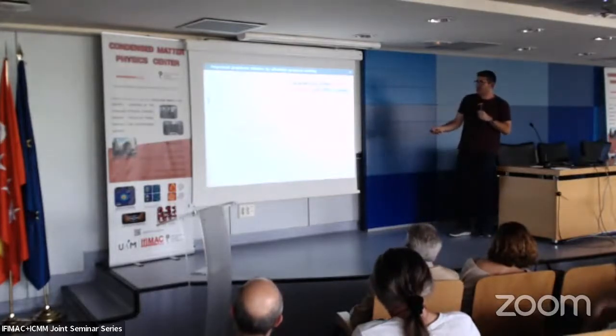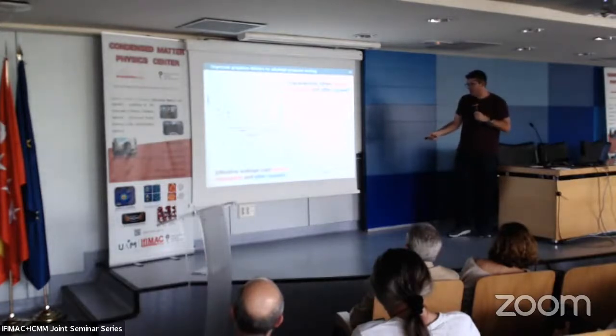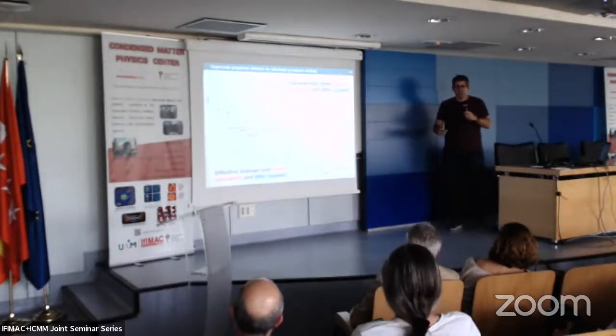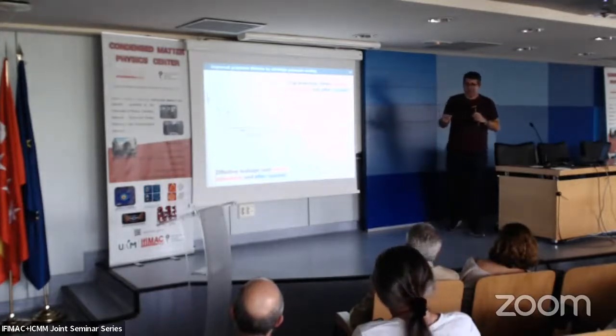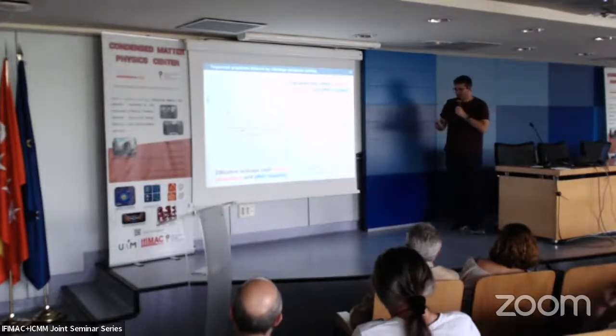If we now study these characteristic times of inflation and deflation at different pressures, at different lids, at different configurations, we can see that after sealing, all the times always go up. And if we go to this model in which we see the effective radius of leakage, we can see that all the effective radius goes down. So this means that we're effectively improving the sealing of these holes, and it's telling us that the main leakage is going through the interface and not through the walls of the wells.